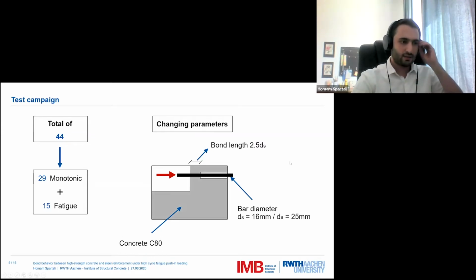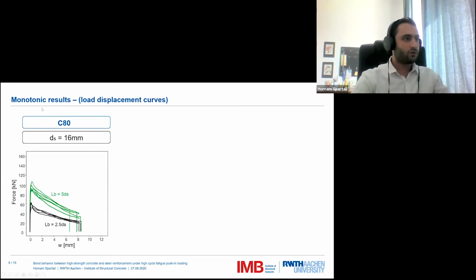However, in the case of concrete C80, we also used another bond length of 5 ds. Now that we know everything about the testing campaign and materials, let's move to the results. In the case of monotonic tests, we applied a displacement of 1 millimeter per minute to the end of the bar. And in the case of concrete C80, we obtained the following results for also the diameter 16 millimeter.